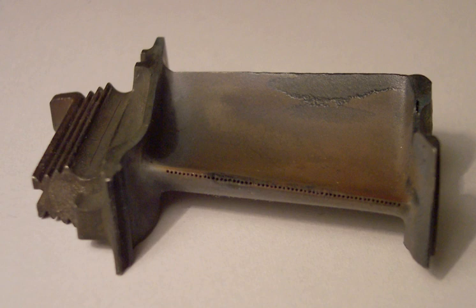The traditional pack consists of four components: substrate or parts, ferrous and non-ferrous; powdered alloy Ti and or Al, C and or zinc, B and or Cr; halide salt activator, ammonium halide salts; and relatively inert filler powder, aluminium oxide, silicon oxide, or SiC. Temperatures are below 750 C. This process includes but is not limited to aluminizing, chromizing, siliconizing, sherardizing, boronizing, titaniumizing. Pack cementation has had a revival in the last 10 years as it is being combined with other chemical processes to lower the temperatures of metal combinations even further and give intermetallic properties to different alloy combinations for surface treatments.